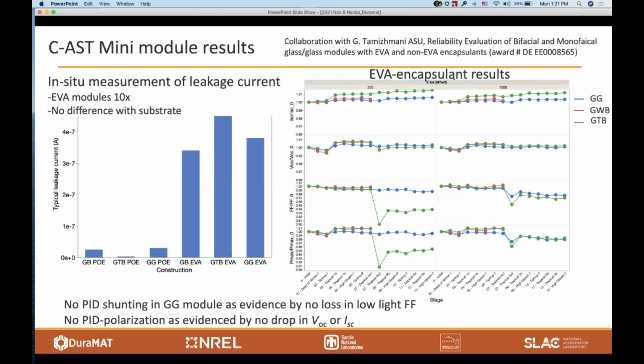So we look at these EVA encapsulated modules and look at the performance over time. And what we're seeing is no real loss in fill factor in low light. Well, we're not really seeing any important drop in power performance, fill factor, and we're not seeing any particular polarization as evidenced by drop in VOC and ISC. So this big elephant in the room is associated with the modules dropping, but you can see in the low light fill factor, which we might look at for evidence of PID shunting, is that it's fairly stable before the break and fairly stable after the break. So that's why I say it doesn't look like PID shunting.